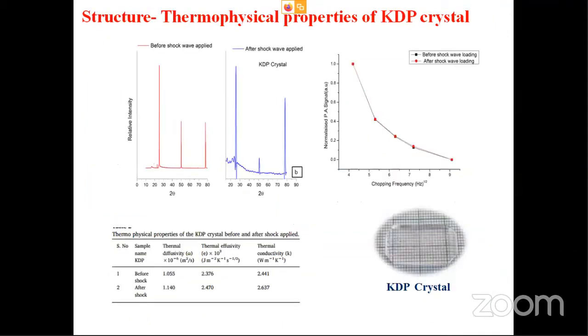The same thing we have done with the KDP crystal. This is the KDP crystal, and this is the XRD. This is before shock, this is after shock, and this is the thermal diffusivity. We could understand that after the shock wave treatment, there is no change in the XRD. This is before shock, this is after shock, and the thermal diffusivity also did not change much. So we can conclude that KDP can withstand shock waves, and it is an optimal material for high power laser generation and high power laser irradiations, because the crystalline nature is not altered. So it is stable against shock waves.